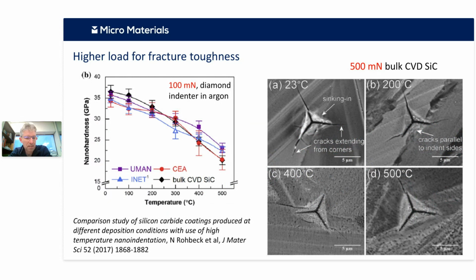In this case, the group in Manchester have got relatively low load measurements on the left to get the mechanical properties, hardness, elastic modulus, as a function of temperature. But on the right, they used a higher load specifically to look at fracture toughness in these. In this case, it's a bulk CVD material, but the same sort of measurement idea, that you can basically look at fracture and again as a function of temperature.